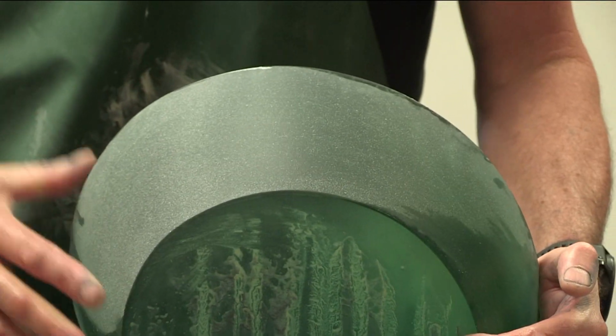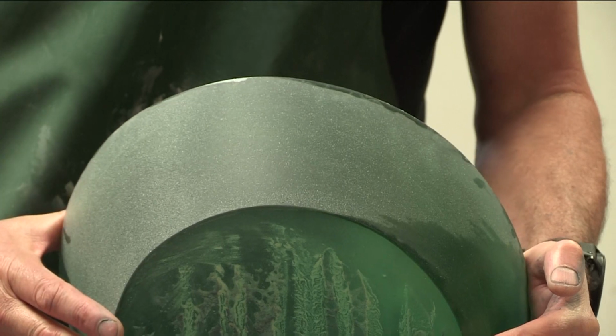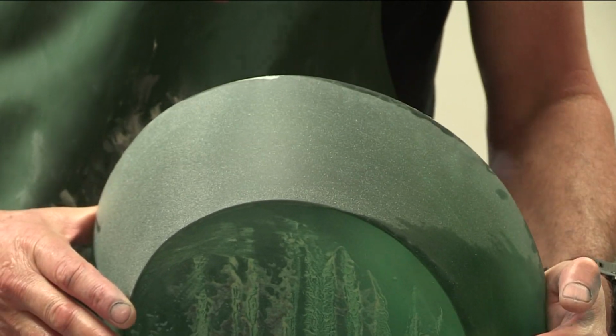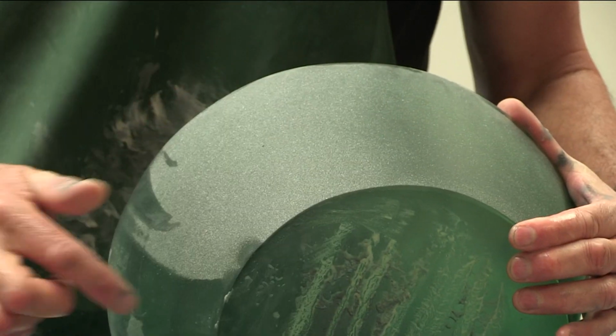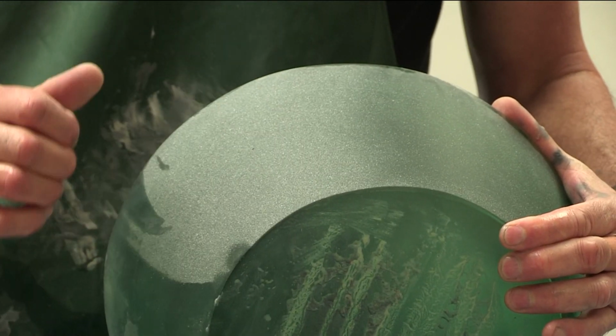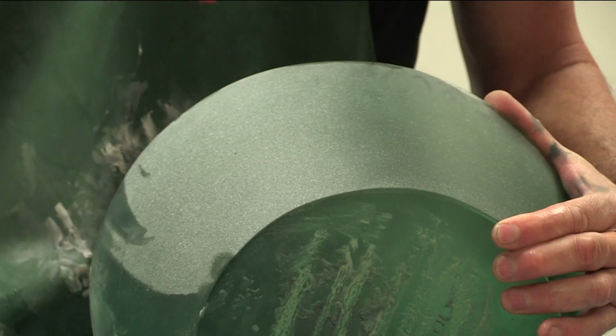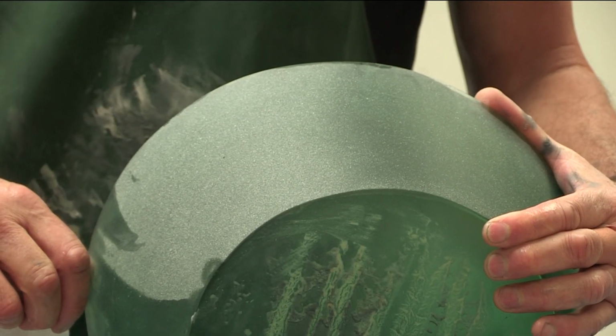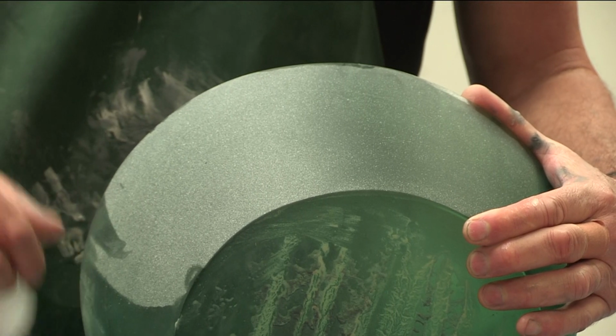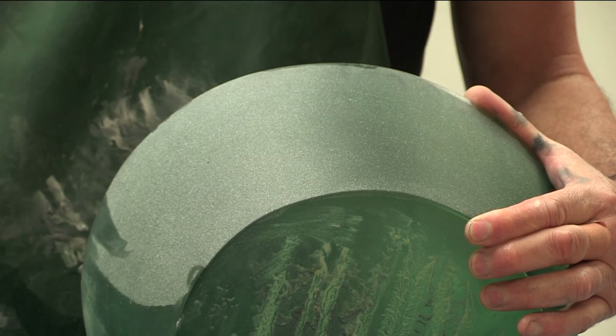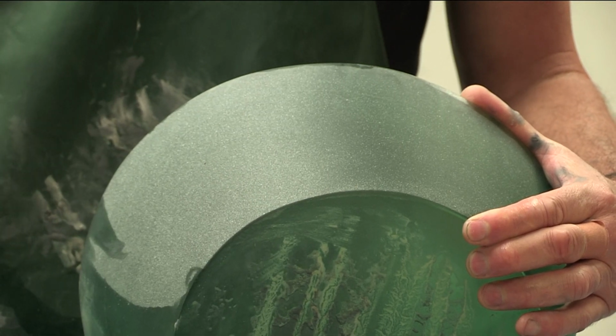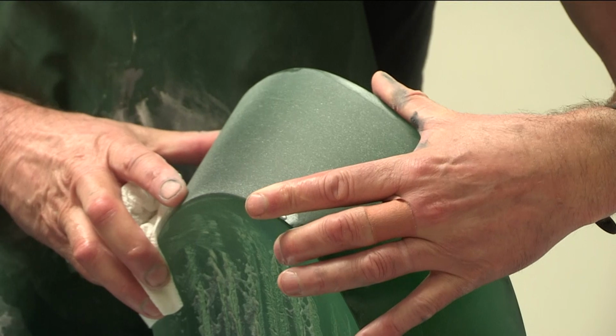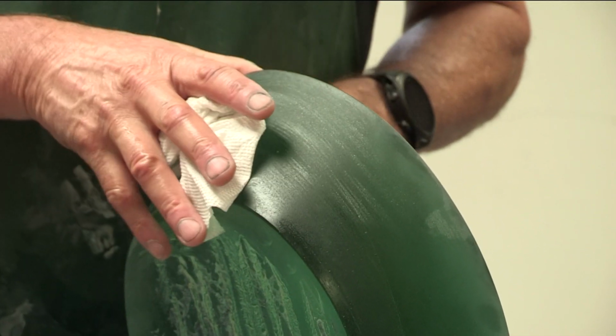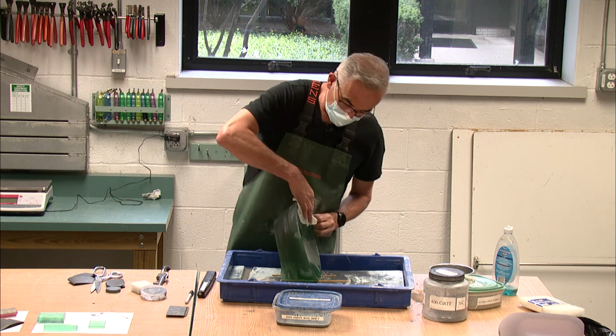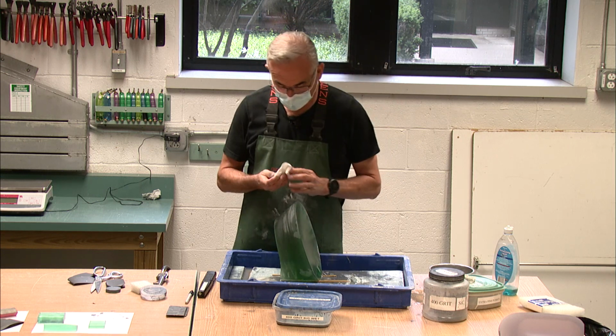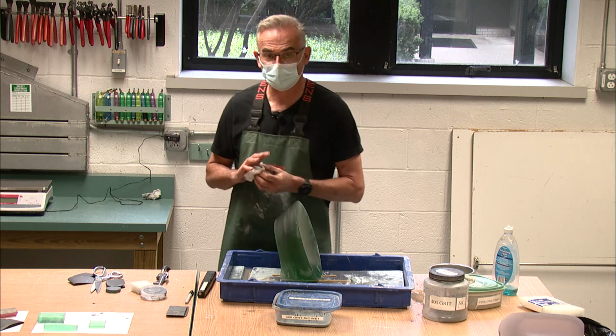You can see there that really nice matte, still got a little bit of a pockmark surface to it, but over on this side here you can see how much starker and whiter it is and flat it is. It almost looks like a sandblast. I really don't like sandblasted surfaces, but if you want to experiment with sandblasted surfaces as well, you can do this same technique. You can put a sandblast on there and then go back with the emery paper and the pumice. So they're just a couple of techniques of how to finish surfaces and how to bring up pieces to finish them without using chemicals or anything like that.